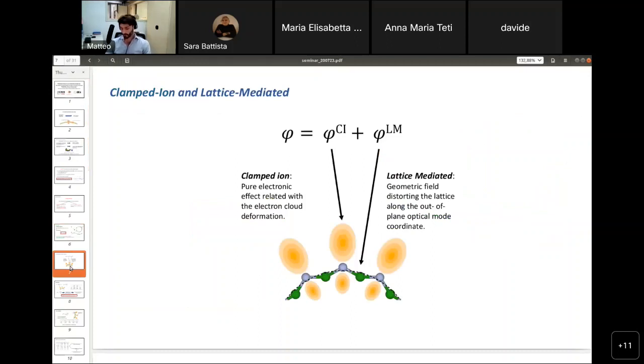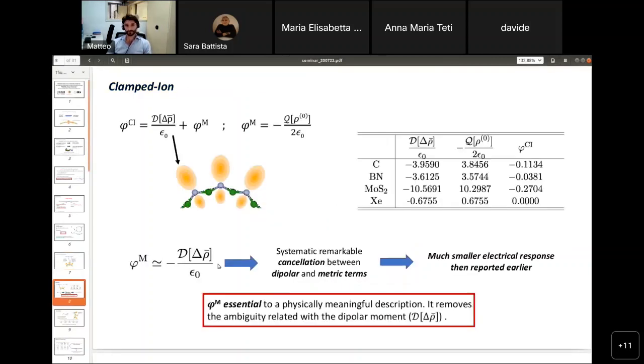Now, generally, whatever the quantity considered in flexoelectricity, we know that the flexoelectric response of a material can always be split into two contributions. One is the so-called Clamped-ion contribution, which is equal to the pure electronic response of the system, thought of as not allowing the internal relaxation of the ions constituting the system. The second one is the contribution arising from the internal relaxation of the ions. Let's begin now by taking a deeper look at the Clamped-ion response.